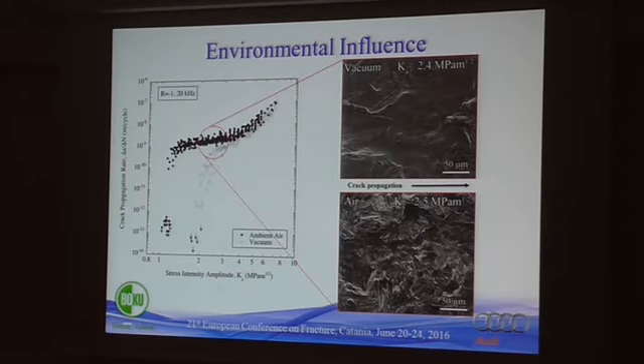But when we go down in the range of crack growth rates where there is a clear environmental influence, we find indeed a pronounced roughening of the fracture morphology obtained in ambient air, featuring these cleavage facets indicating that some sort of embrittlement has taken place in the material. Whereas in vacuum, the fracture surface tends to smoothen, featuring areas of fine granular appearance and numerous deformation traces.